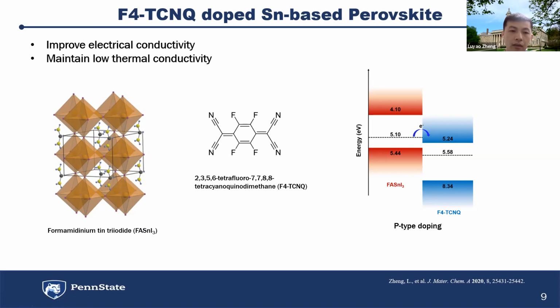And rather than doping inside of the lattice, trying to replace an atom in the lattice, here we try to use some small molecules to dope the material at the molecular level. Because this F4-TCNQ has a low-lying LUMO energy, when it is mixed with or doped into the FA tin iodide, the electron will transfer to the F4-TCNQ, because the Fermi level of the FA tin iodide is around here. That way, we can induce more holes inside of the FA tin iodide, leading to p-type doping. This is a way to improve the electrical conductivity.